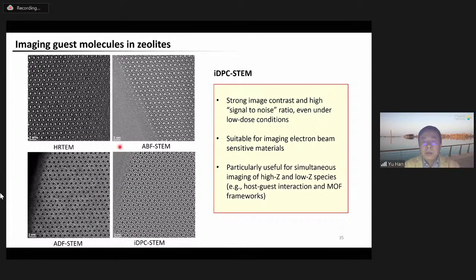Here we use different imaging modes to image a zeolite material, which has absorbed some hydrocarbon compounds in the microporous channels. As you can see, this is the normal HRTEM, this is the bright field STEM, dark field STEM, and this is the iDPC-STEM. Compared to the normal HRTEM or standard STEM, the iDPC-STEM gives the best image contrast for the zeolite framework. And more importantly, it shows the presence of the organic compound in the channels very clearly. You see in the channels, there are organic compounds.